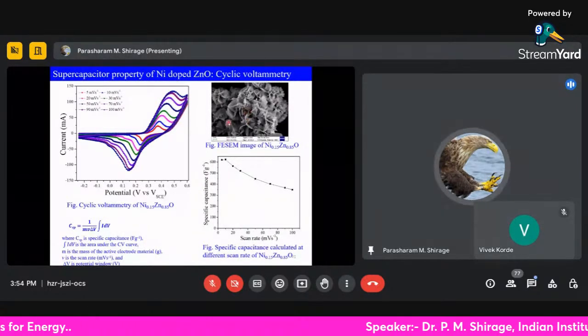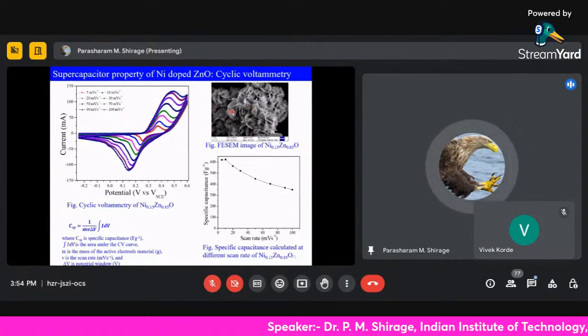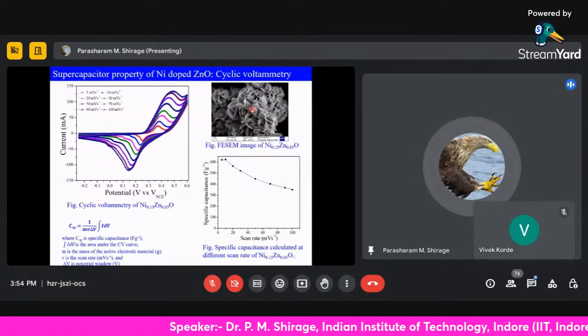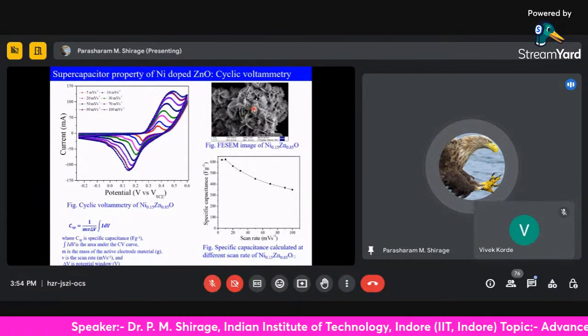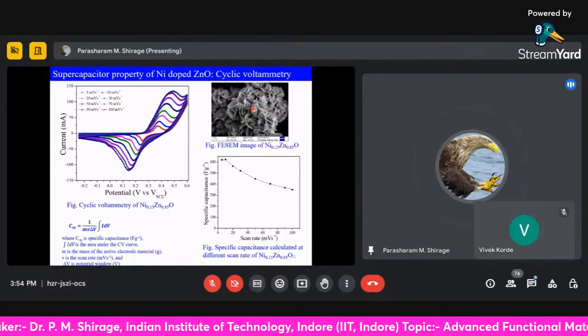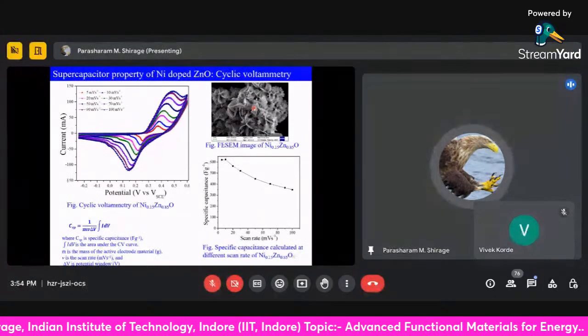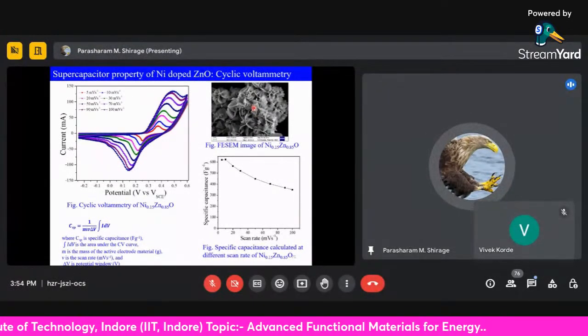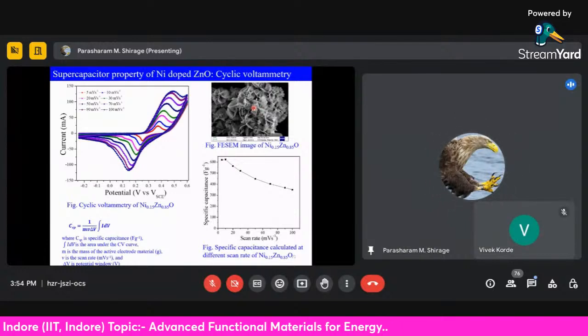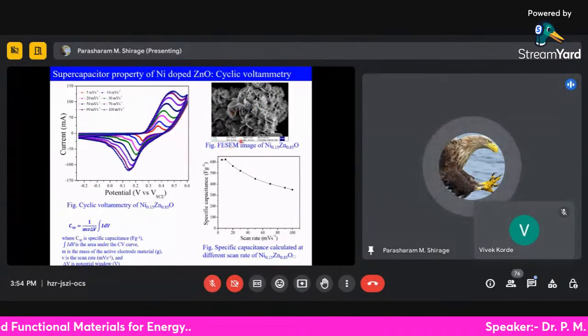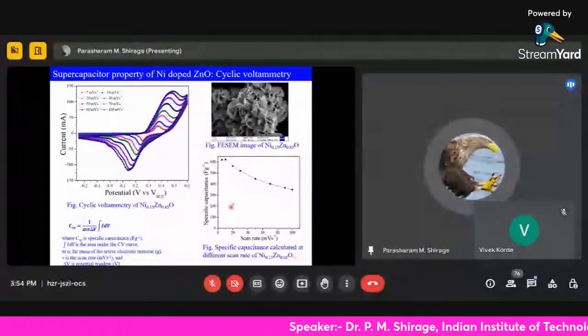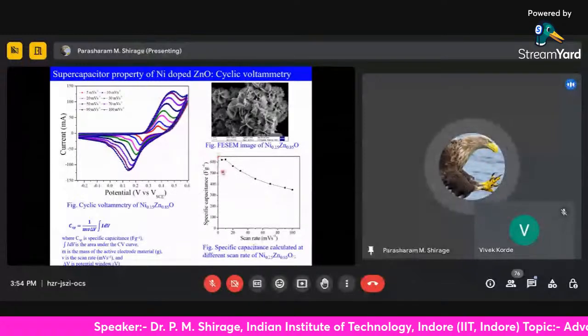And this is 15% nickel doped zinc oxide, and you can really see that earlier, when nickel was doped in zinc oxide, it was a rod-like structure. At 15% atomic percent doping, it is a completely tower-like structure. And when we measure the specific capacitance of this at different scan rates, we can see a maximum of 600 Farad per gram of this material.